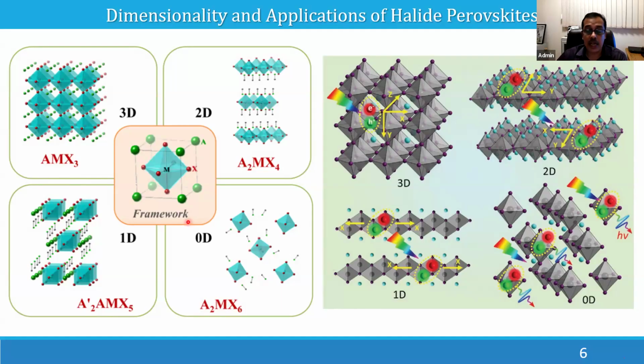If you use a slightly bigger or slightly different organic cation, you will end up with isolated octahedral structures. Like this, isolated octahedral structures. Still, it is a perovskite structure, but the octahedrons don't have any electronic interaction or communication between them. So if an exciton is formed in one octahedron, it will remain there, and that exciton will be highly bound. The energy of interaction will be very, very strong.